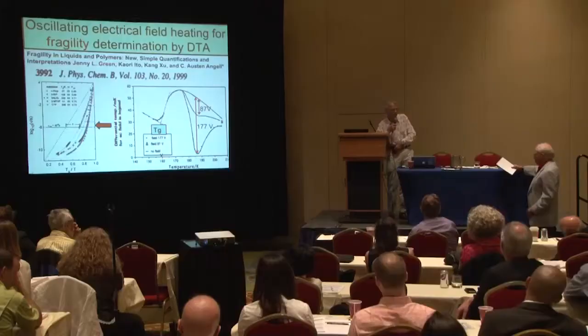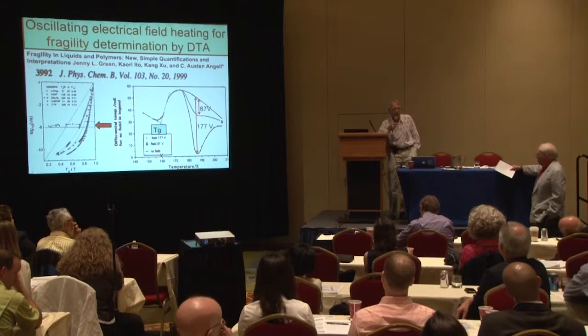You can, if you're willing to apply the Clapeyron-Clausius relation, the Clapeyron equation actually, to the coexistence between the two polymorphs of water, because that has a volume dependence. There's a difference in volume, Valeria gave you an estimate of it, between the two competing forms of water which are involved in this critical-like phenomenon. As you raise the pressure, you can see the evidence for this by the decrease in the rate at which the compressibility and the heat capacity, for that matter, rise anomalously.